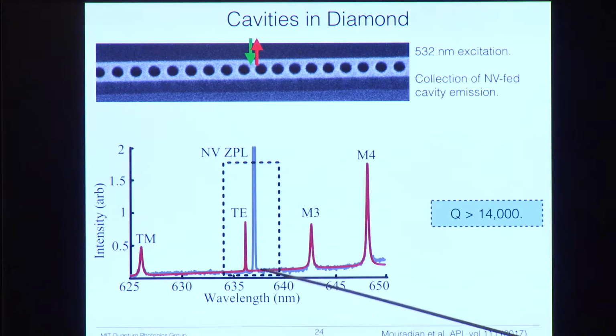So what we care about is the quality factor of this. We can measure with a spectrometer up to around 14,000, and that's what we measure, a Q of 14,000. So the actual Q might be a bit higher, but we already know that it's 14,000, which is, and still is, a record for diamond nanophotonics at visible wavelengths.